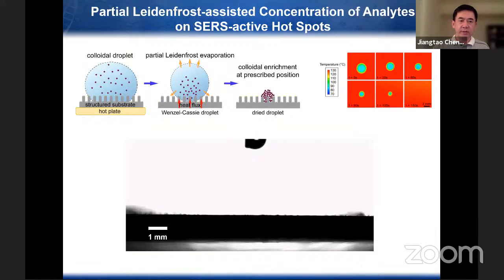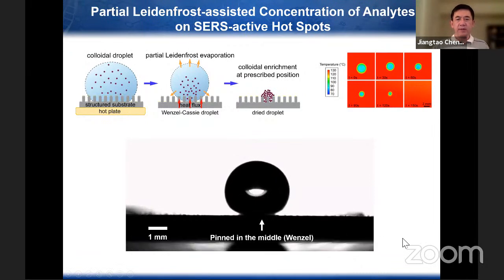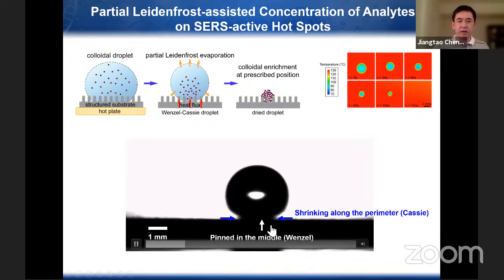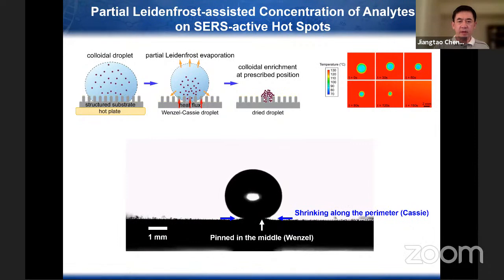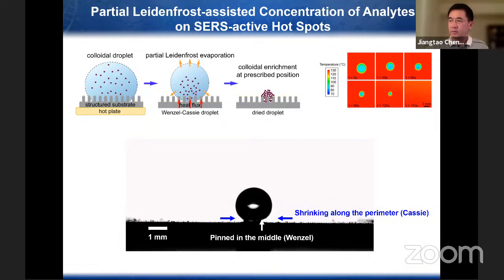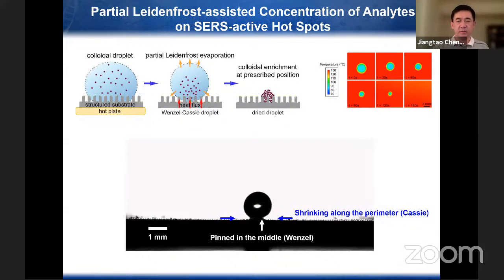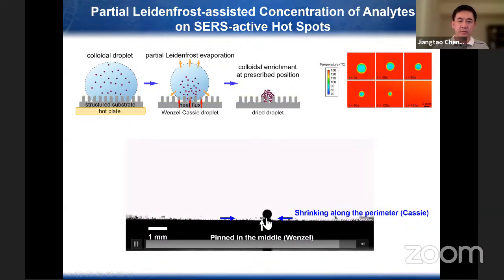And this movie shows the partial Leidenfrost evaporation based enrichment of the droplets. So we can see the evaporation on the hot surface shows continuous shrinking along the perimeter of the droplet. But in the middle of the droplet base, it got pinned, which means the droplet will stay on the surface. And finally, the significantly enriched analytes will be deposited on a footprint of only tens of micron scale. Okay. So we can see the pinned analyte droplets, and the footprint is only tens of microns wide.